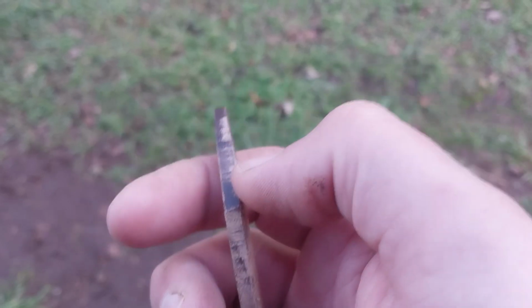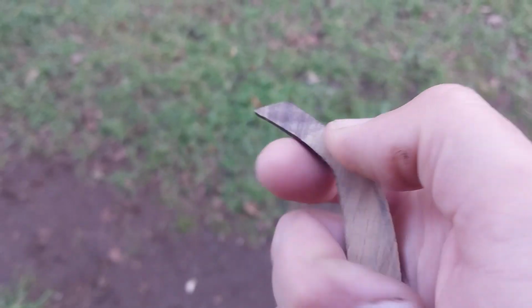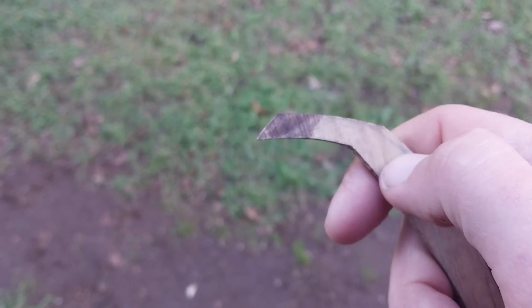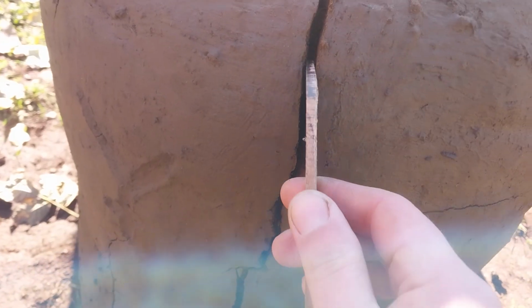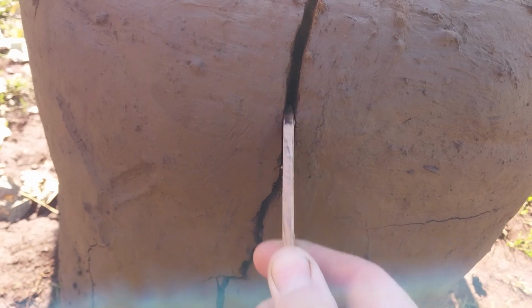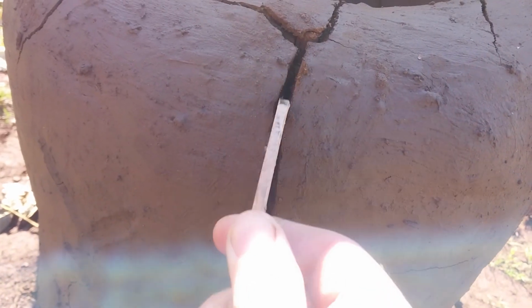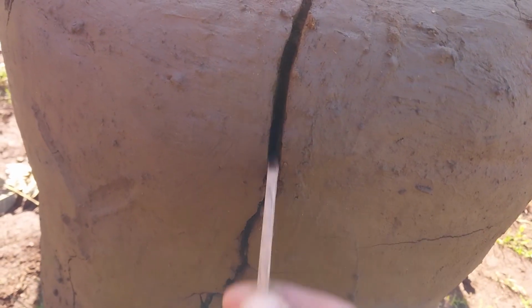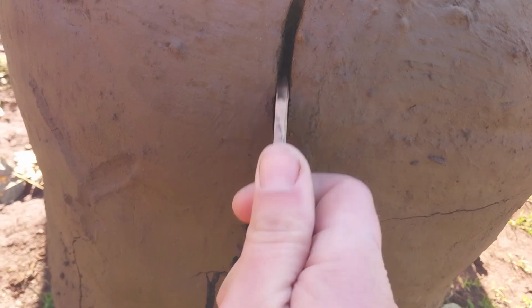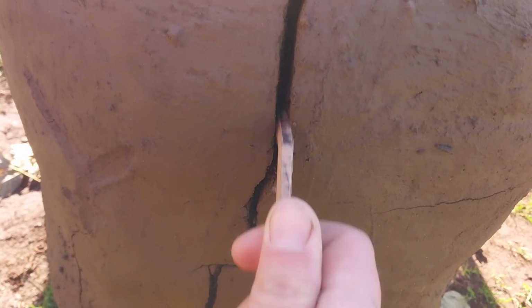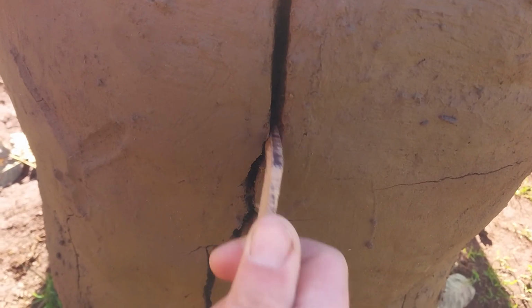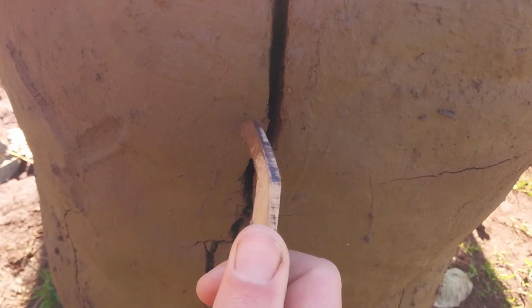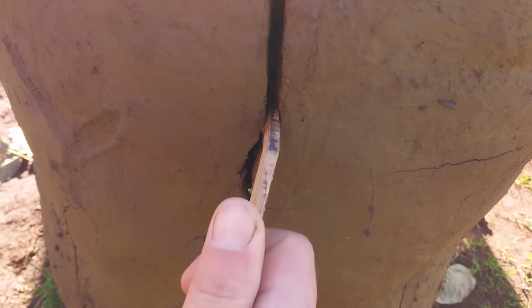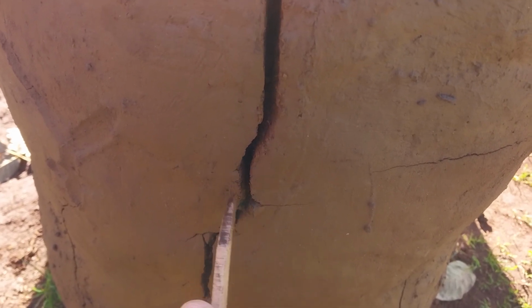If we have to, we can move it side to side to widen the crack, but this gives us good leverage to very gently scrape out the inside. And it's as simple as just working it in. And you see how the clay is just not crumbling as I do this? It's staying really clean on the sides. That just goes to show this is not a structural crack. This is literally just settling and expansion.